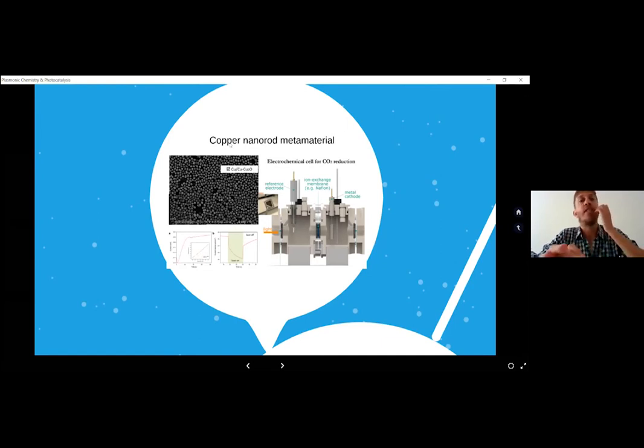And this is the work from Anastasia, from King's as well, where she has been working on the electrochemical CO2 reduction and plasmon excitation on these copper metamaterial nanorod surfaces. This is similar to the previous example where we have a template, and then, in this case, copper and copper oxide on the surface. This material can also support plasmonic resonances, and you can excite the material and also perform electrochemical measurements, right? So you can do photoelectrocatalysis on this metamaterial, exciting the plasmons and electrically contacted in this cell.